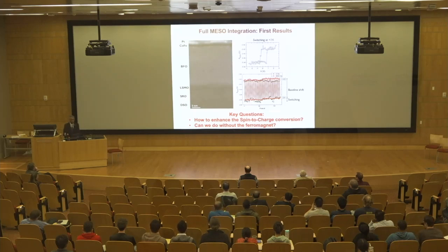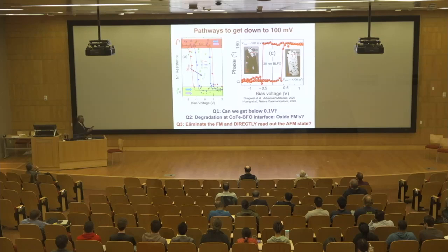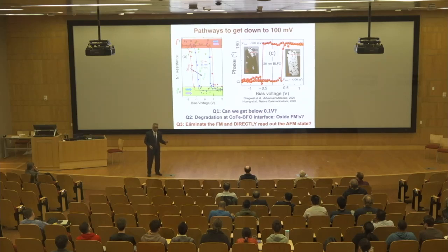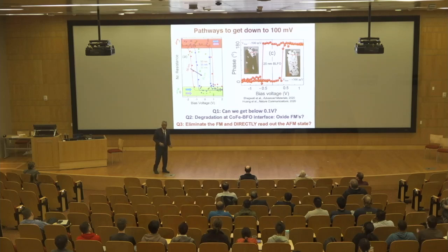Actually, this is perhaps very exciting to me. Let me just summarize. This is where we are. We know that we can go to about 10 to 20 nanometers. We still don't know how to do careful measurements at a few nanometers. Electrical measurements is not that trivial. That's a big challenge for us, especially in real devices. But we know that the ferromagnet will switch back and forth. This is measured using photoemission microscopy at about 500 millivolts, maybe 200 millivolts. 100 millivolts is still a challenge.